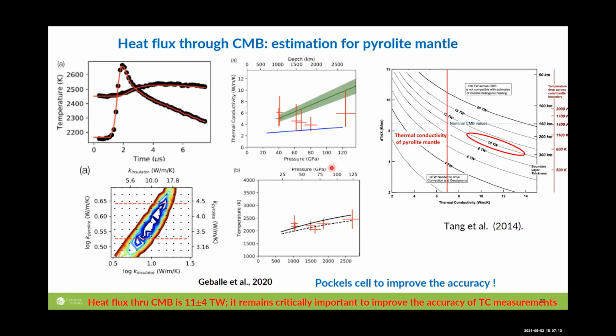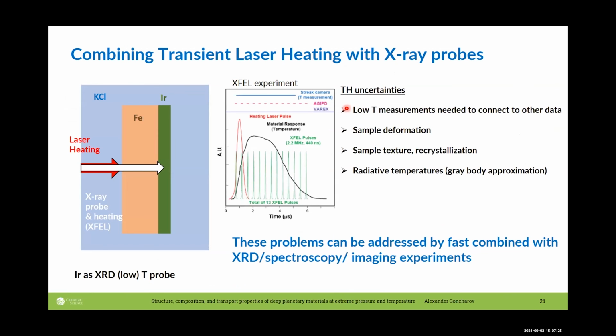So I briefly discuss here the pyrolite measurements where we determine thermal conductivity. And this slide is important to understand that the error bars of our experiments are quite high, and we need to make them smaller. To make them smaller, we need to do a number of things. For example, again, perform low temperature experiments and combine them with other experiments where we can make diagnostics of the sample in real time when we do laser heating.